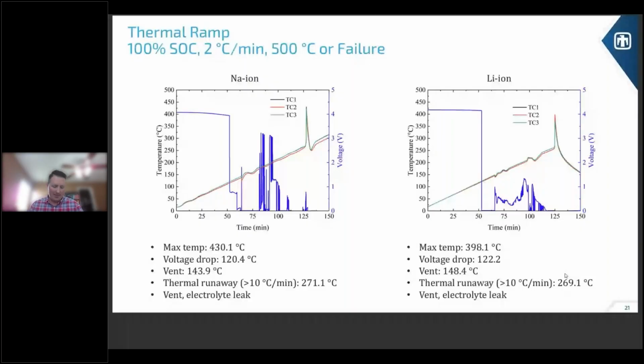Okay, so as I described from the external short, the sodium ion showed us more than the lithium ion. Like I said, there was a vent and leaking, which we don't normally see for lithium ion. So that was interesting. And I think it's a product of what Ramesh said, the sodium ion cells can be a little bit more performance based in the discharge aspect, which, as I said, we discharged more in that external short. So we see that.